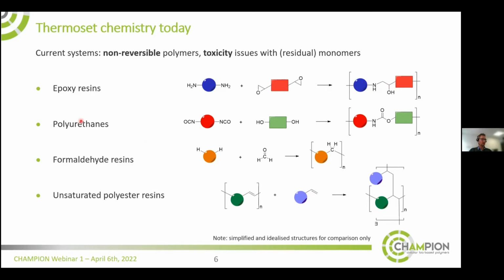A second important class of thermosets are the so-called polyurethanes. In this case, you take a so-called isocyanate and you react it with a polyol and you end up with a polyurethane. And this is the urethane linkage. A third important class of thermoset resins are the formaldehyde resins. And here you have phenol formaldehyde, urea formaldehyde, and melamine formaldehyde. And in this case, you take one building block, which could be phenol, melamine, or urea, and you react it with formaldehyde. And then you form a cross-linked network known as PF, UF, or MF materials.